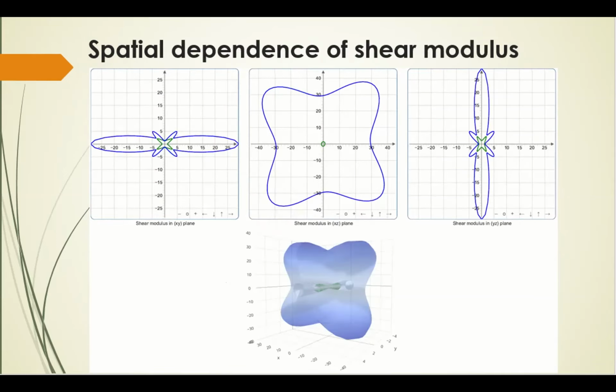The next is the spatial dependence of shear modulus. The green curve shows the lower limit, known as the Reuss limit, and the blue the upper limit, also known as the Voigt limit. If this value is low, the material is softer, while if it is high, the material is harder. It ranges from about 1 GPa to 48 GPa, where the XZ plane has the highest anisotropy.